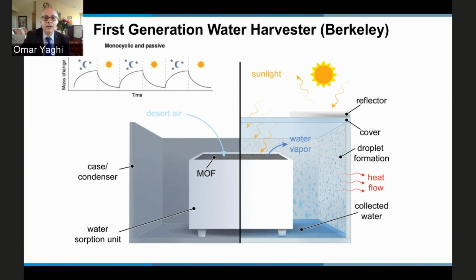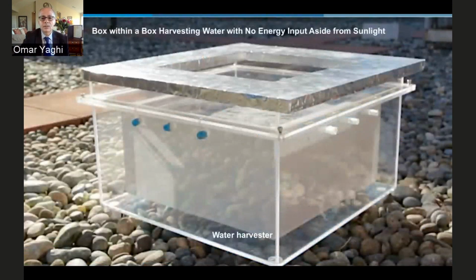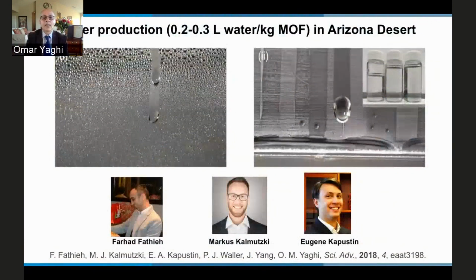And so we took this to Arizona. This is what the box within a box looks like. It's fairly simple, just two plexiglass boxes. But now you can see the condensation on the walls, and the students took this, as I said, to the Arizona desert and were able to harvest 200 to 300 milliliters of water per kilogram of MOF. Okay, so this is a success. The MOF works in the desert with no energy input aside from sunlight.